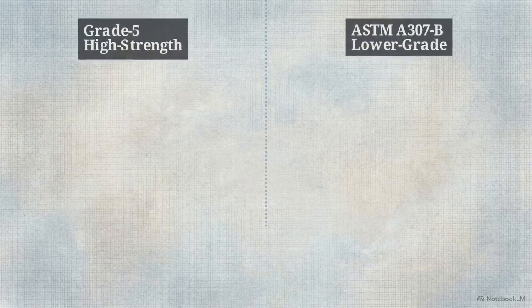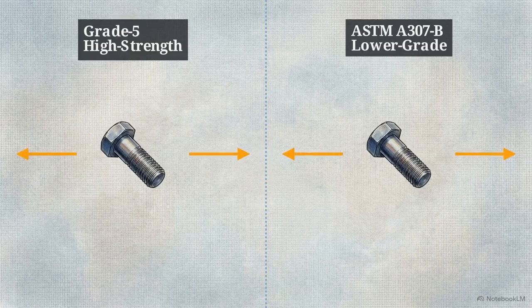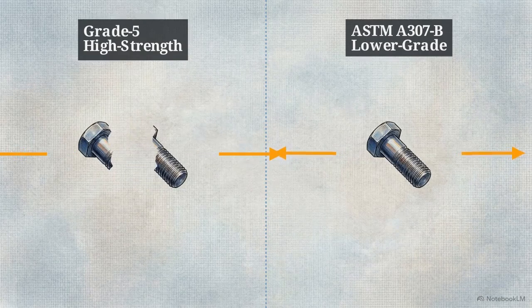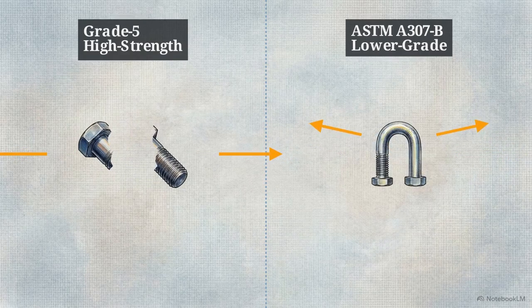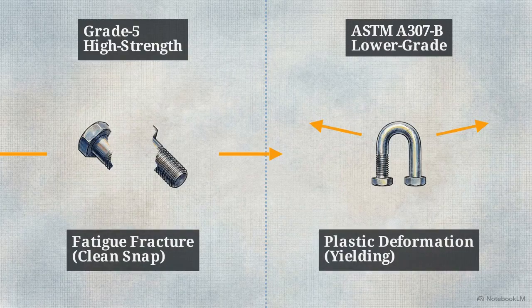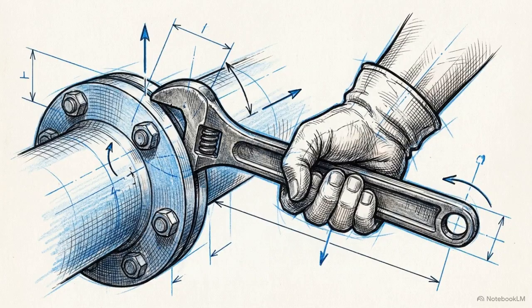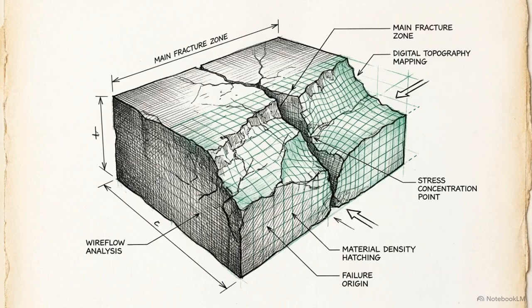The physical evidence presents an immediate mechanical contradiction. High-strength steel fasteners snapped cleanly across their diameters, while softer, out-of-spec bolts in the same assembly yielded and bent without breaking. The grade 5 bolts fractured when human error at the time of assembly intersected with a precise geometric vulnerability in the joint design. To trace that sequence of events, we have to look past the macroscopic damage.